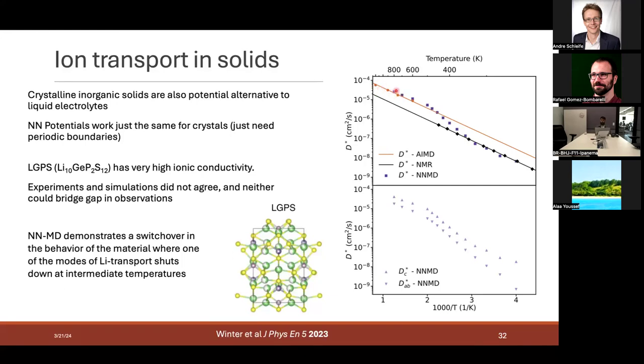And they get this red trend. And then the experimentalists can measure diffusivity with NMR, and then they get the black squares. And the two things have more or less the same slope, but there's like a full order of magnitude difference between what the theories say this material should do and the experiments say it does.